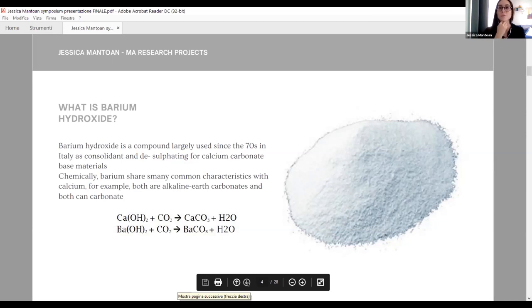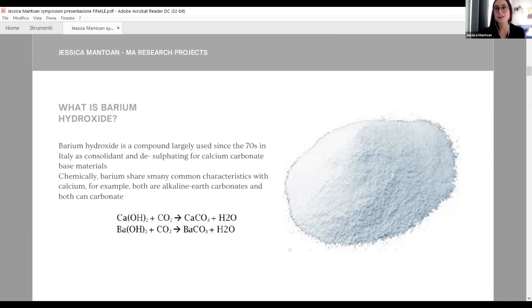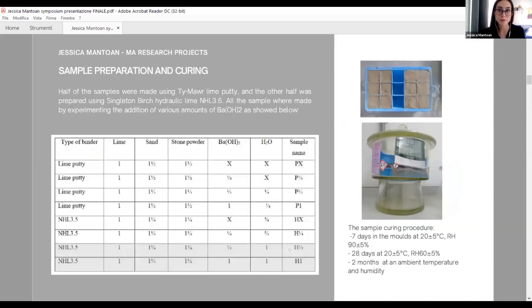In general, barium compounds, in particular barium carbonate and barium hydroxide, share many chemical characteristics with calcium compounds. In particular, both of them are alkaline earth compounds, but most of all, both of them are able to carbonate, as the reaction in the slide shows here. And starting from that, I developed all my research, because when I realized that barium hydroxide was able to carbonate exactly as calcium hydroxide does with carbon dioxide, I started to believe that it was possible to create a mortar with this kind of double binder, partially made of calcium carbonate as in traditional mortar, but the other part made of barium carbonate. And it's exactly what I did in the preparation of the samples.